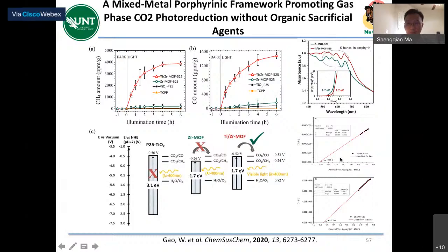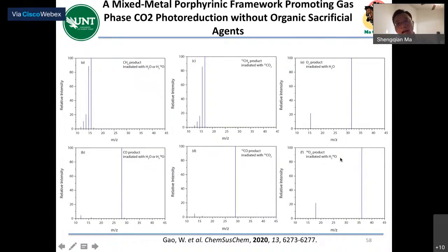And this is some characterization I will skip. And we did a lot of isotope studies. This is carbon-13 from CO2. Okay, carbon-13 labeled carbon dioxide, sorry. And also we did the oxygen-18 labeled. Okay, we found that it produces oxygen from water, and also carbon monoxide from CO2. So basically, we figured out the mechanism as we expected.